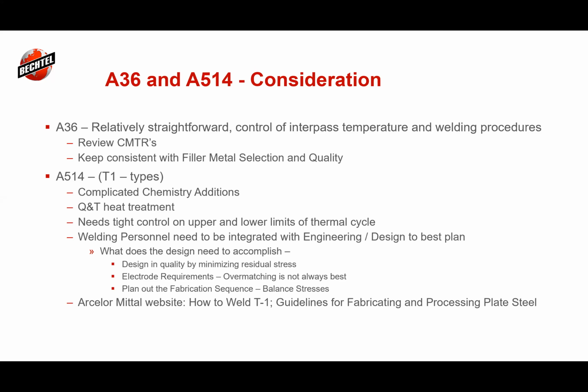I think the big thing with the A36 is just being consistent with that filler material selection, the quality of it, making sure it doesn't keep hot for too long. The 514 is really complicated. There's a lot of chemistry additions. The quench and tempered heat treatment really makes it that you can't do high levels of preheat. You really need to monitor that inner pass temperature. And you don't want to have too low a heat input or too high.